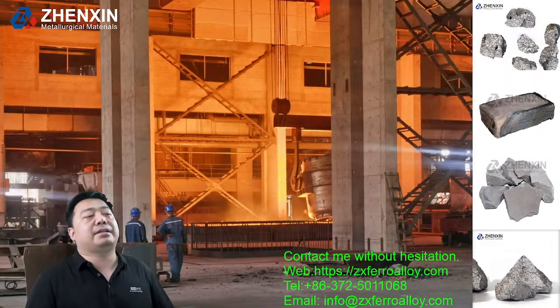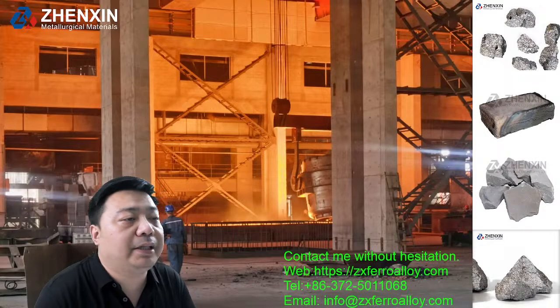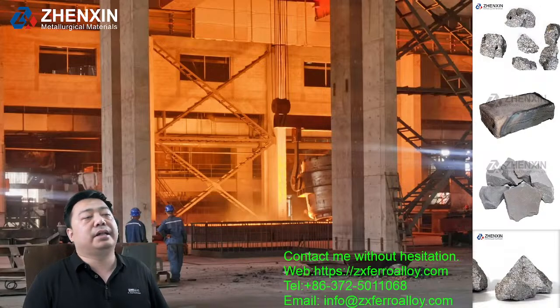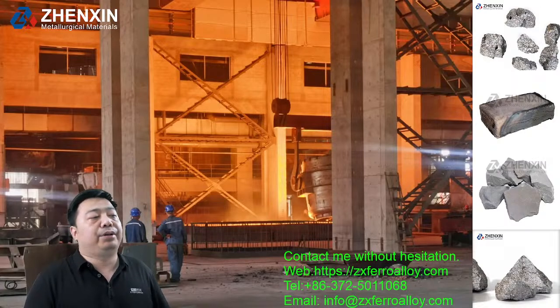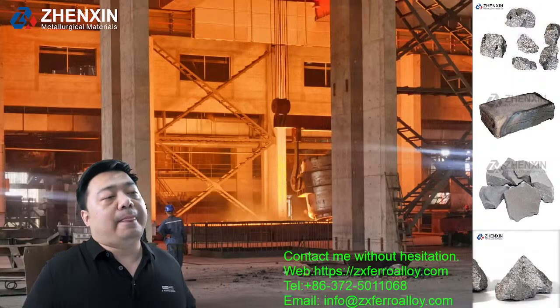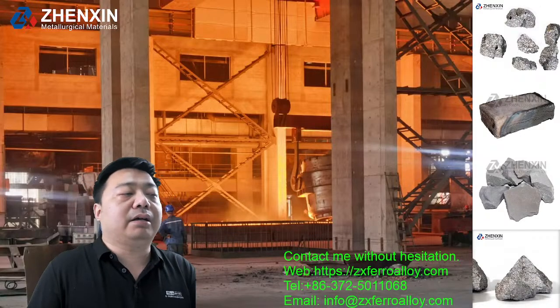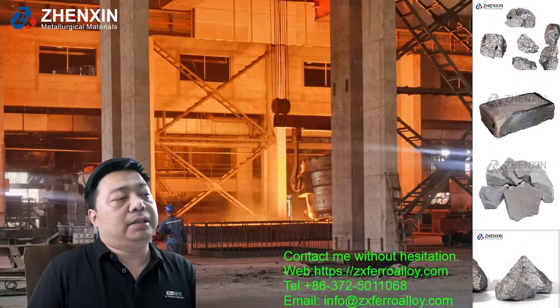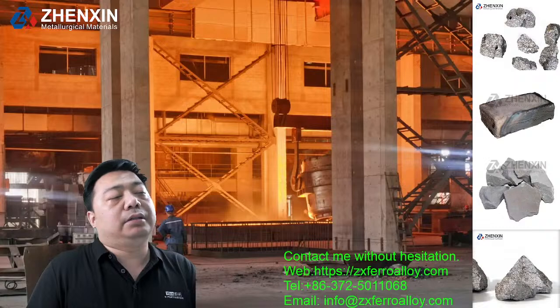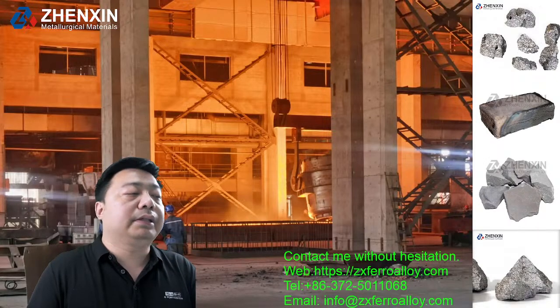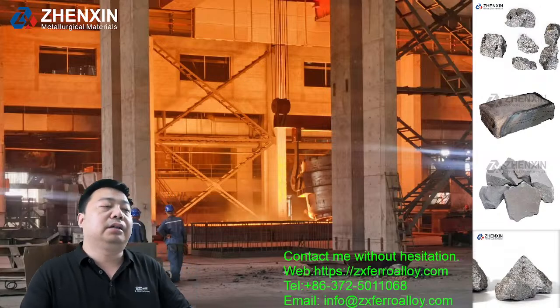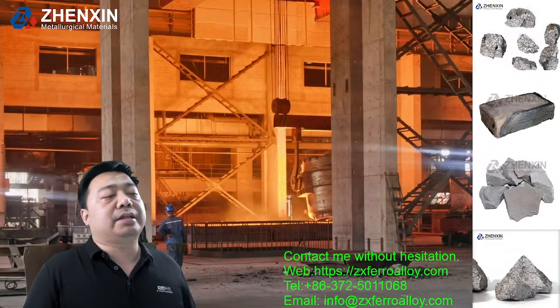In order to adjust the gas permeability of the charge, it is necessary to add an appropriate amount of wood chips during the smelting process, and an appropriate amount of salt is also required to prepare green silicon carbide. The silicon carbide production equipment uses a dedicated silicon carbide electric furnace. When the power of the electric furnace is turned on, silicon carbide production starts.